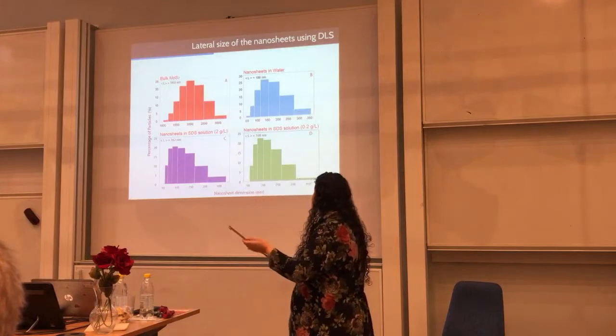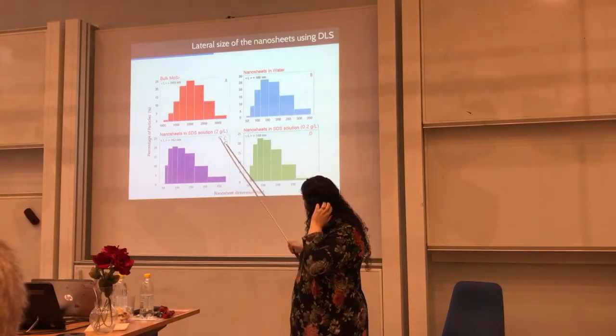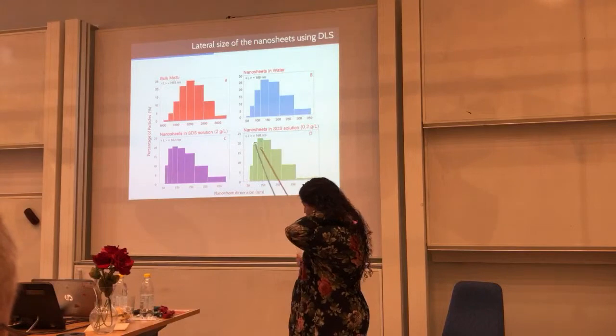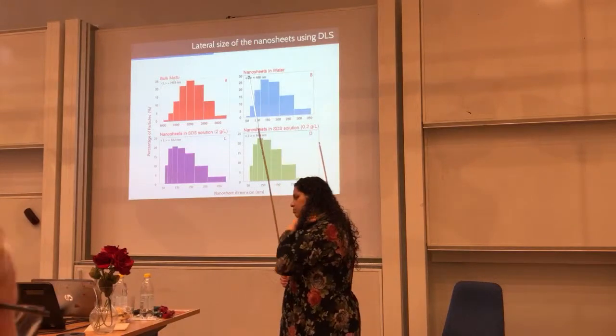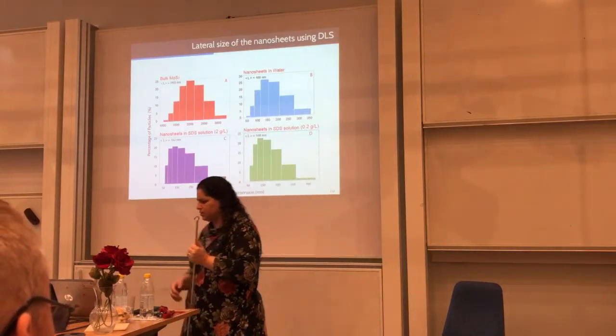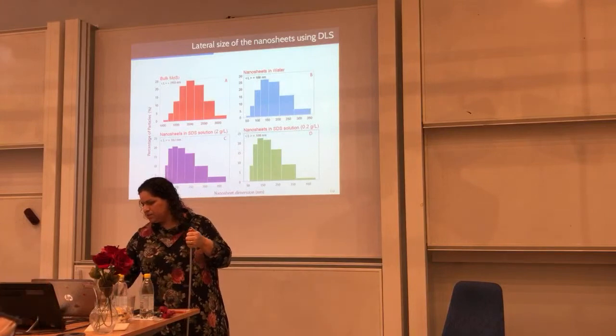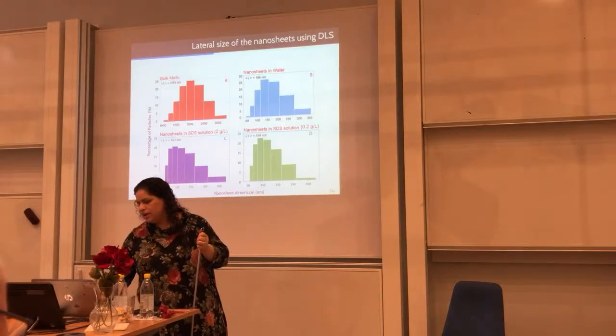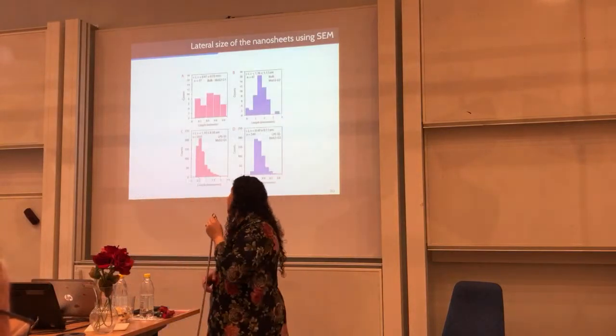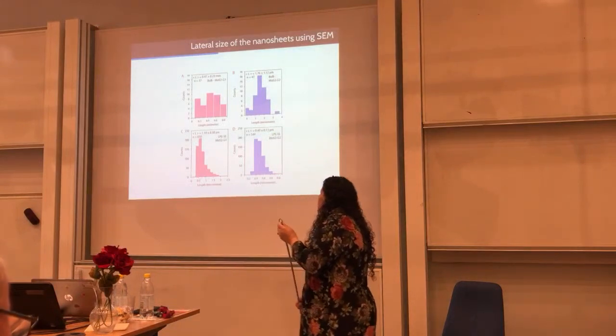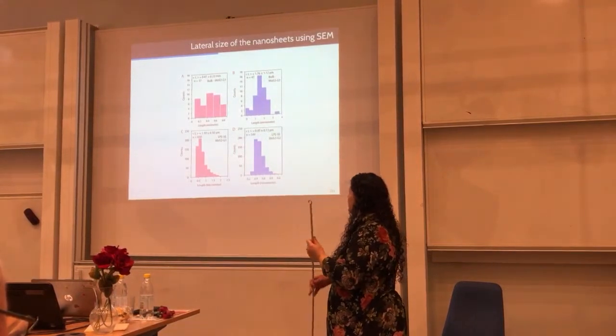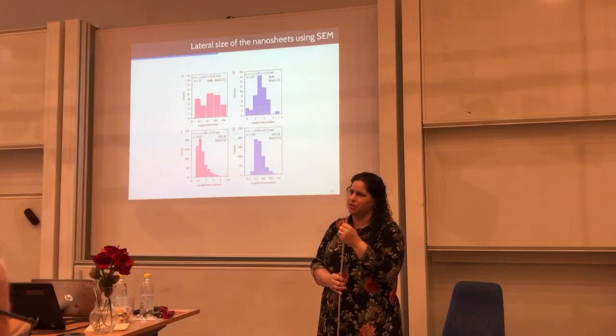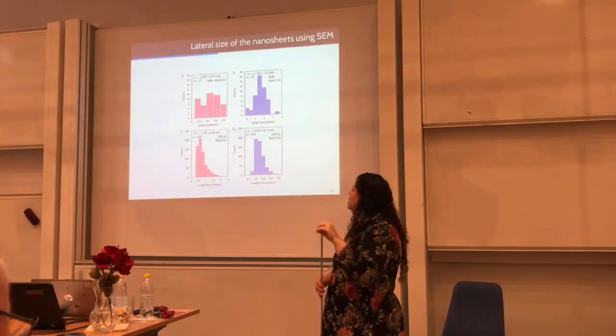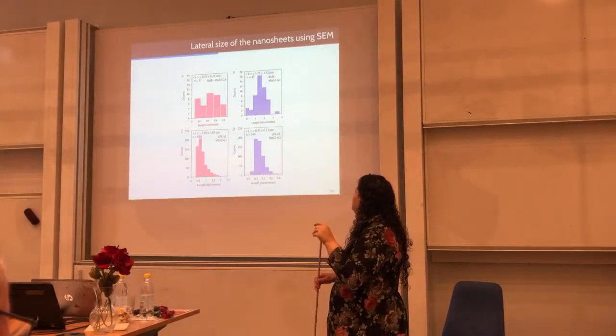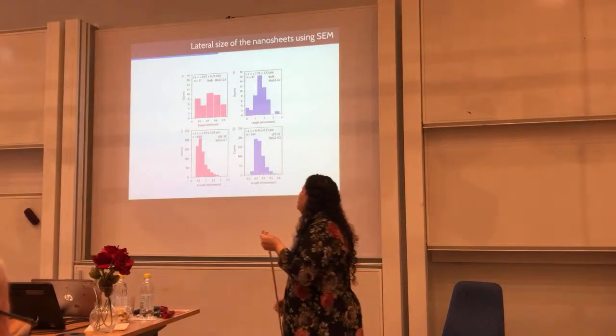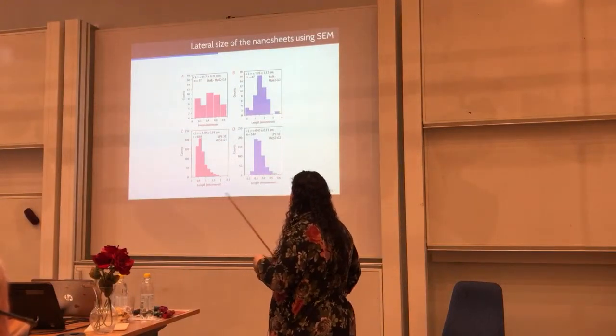What this means is that even though it didn't really depend on the concentration, the size range was the same. Which means that you could reduce the concentration of surfactant quite a lot. This also means a positive point for scalability and commercialization. We always have to think about how to reduce the amount of material used. That's chemical engineering thinking: reduce the time of production, reduce the materials you use.